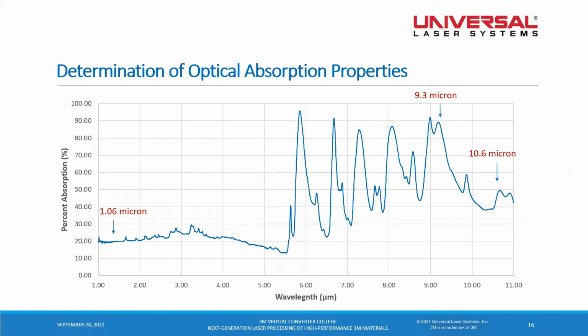This chart represents an analytical measurement of each material, showing from 1.06 micron, which is a fiber laser wavelength, to 10.6 micron CO2, where is the highest level of absorption? In our case, we offer all three of these laser wavelengths. As you can see, the 9.3 micron is the highest level of absorption. It's approximately 2 times better absorption than a 10.6 CO2. What this means is that the laser energy will be absorbed, or more work will be done, with the 9.3 laser in comparison to the 10.6.